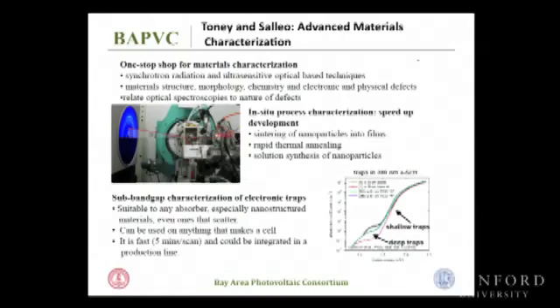So with all this materials development and processing development within the consortium, we also need to have techniques to look at what's happening. We funded a project led by Mike Toney and Alberto Salleo at Stanford right here to develop advanced materials characterization techniques, including using synchrotron X-ray to monitor during the process, when you have a film formation, when you make a new material, what's happening structurally and in chemical bonding, and also looking at the defect formation using advanced optical spectroscopy such as absorption to look at the defects within the band gap. We see it's necessary to have people developing characterization techniques working closely with the teams developing new materials such as CZTS.